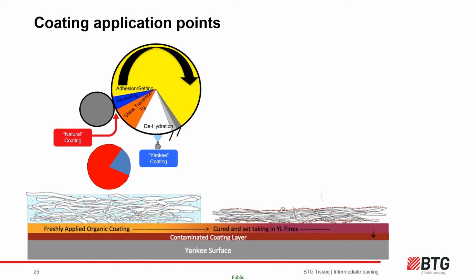The ones that go to the Yankee side will become stuck in the coating, eventually trapped in the coating matrix as it cures. Fines and other contaminants then add to the cured base layer, which can also make it become very hard very quickly and less flexible than just a hardened but flexible polymer base.